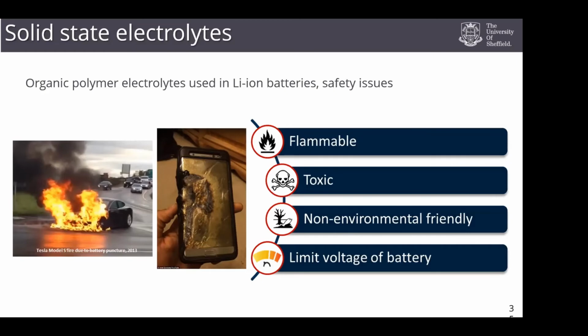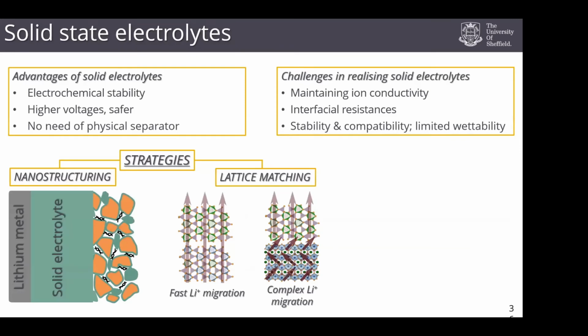The only challenge with that is, I mean, there's lots of challenges with that. Great positives, though: it could be very stable, and all the additional bits and pieces inside a battery cell, like the separator, the solid electrolyte could do that job. The challenge is conductivity. If you imagine two solids, a cathode and a solid electrolyte, you're asking them to meet and marry and to like it, in such a way that it facilitates lithium or sodium ions to move between the two. And they may not like each other very much. They may not be particularly compatible with each other.